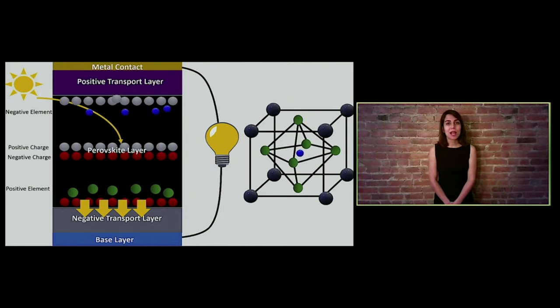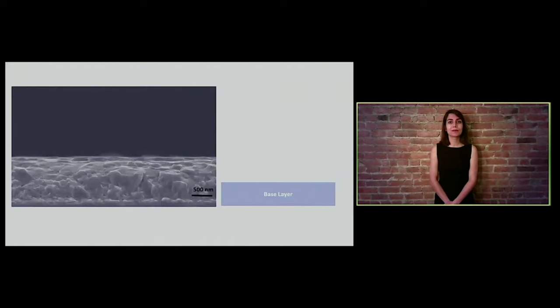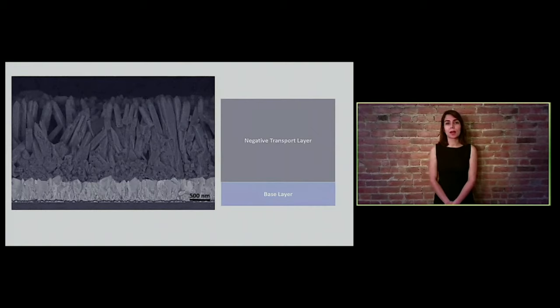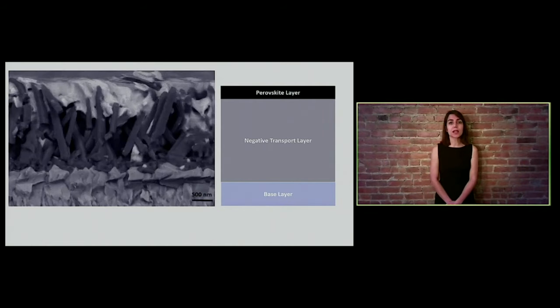Let me show you what I do in the lab to achieve that goal. I start off with a piece of conductive glass as my base layer, and then using some high temperature and high pressure processes, I make these rod-like structures on a nanometer scale, or as we call them, nanorods. Then I infiltrate these very small structures with the perovskite layer, and to finish things up, I deposit the positive